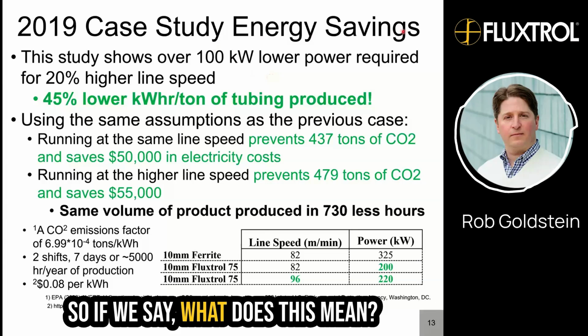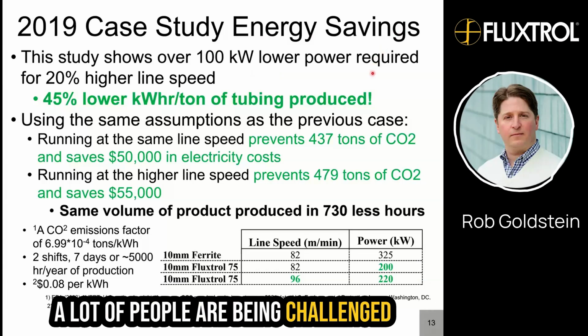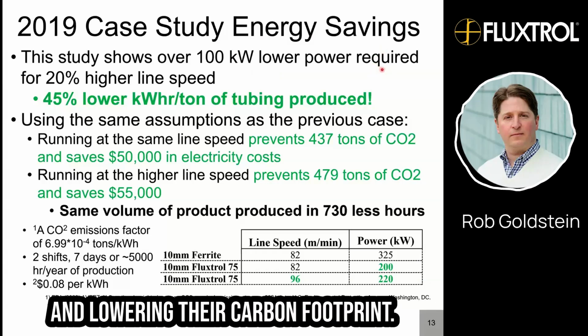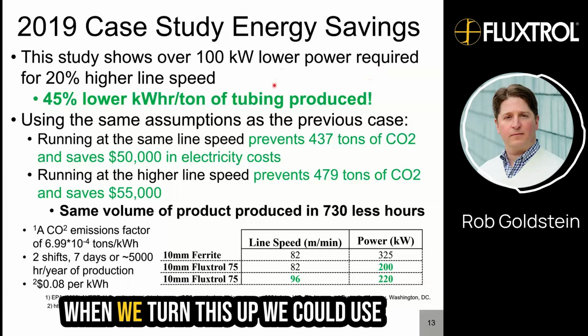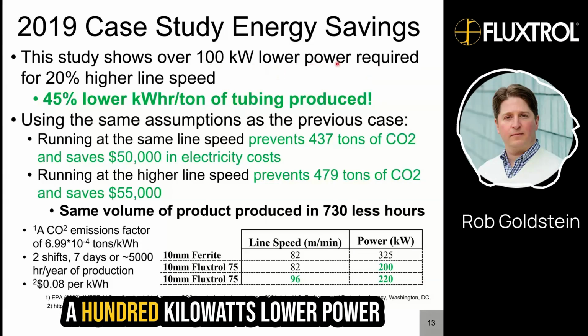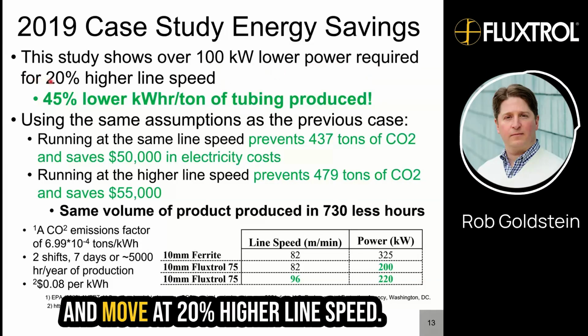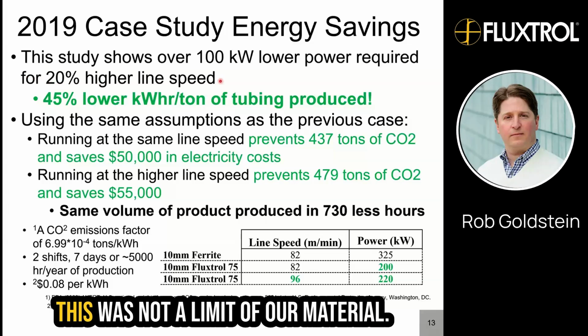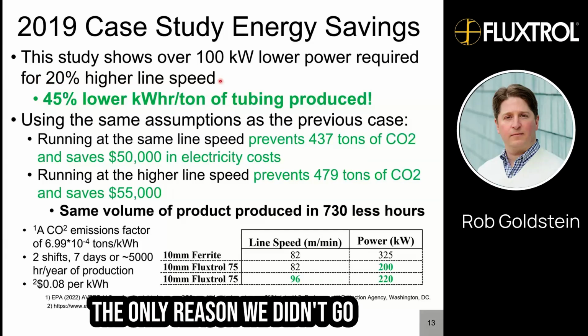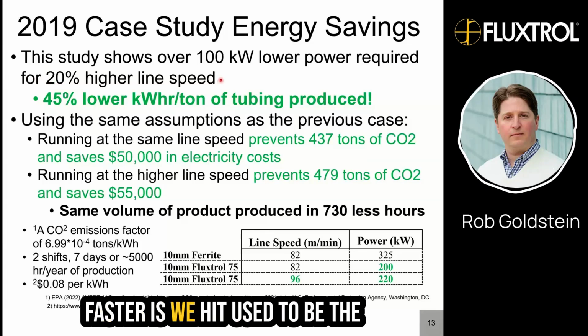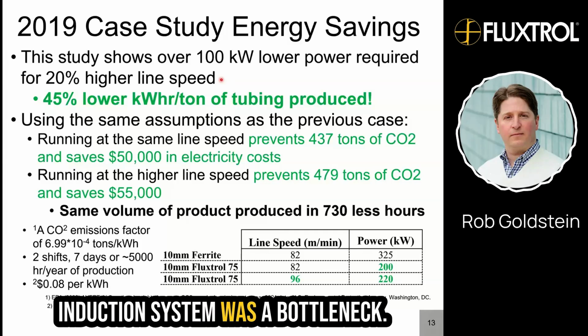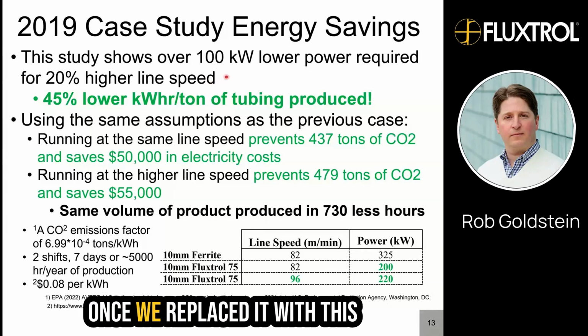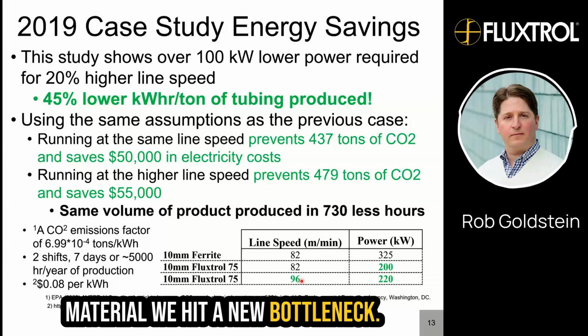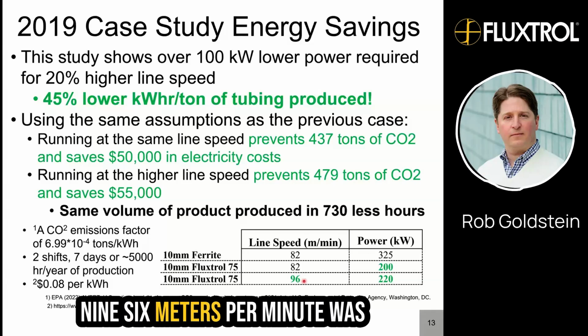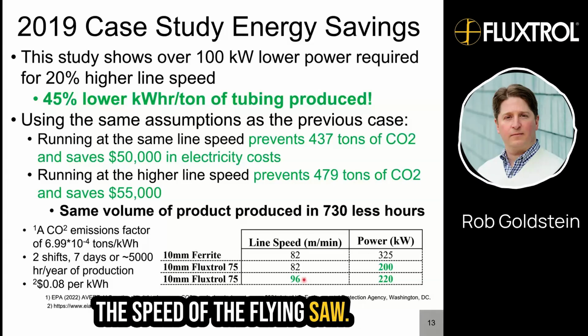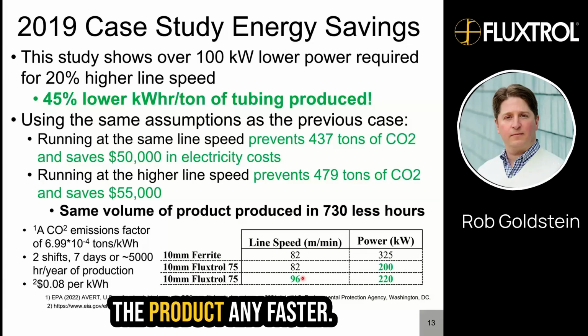So what does this mean? A lot of people are being challenged with reducing their carbon usage and lowering their carbon footprint. When we turn this up, we could use 100 kilowatts lower power and move at 20% higher line speed. This was not a limit of our material. The only reason we didn't go faster is that the induction system used to be the bottleneck. Once we replaced it with this material, we hit a new bottleneck. The next bottleneck we hit at 96 meters per minute was the speed of the flying saw, so they couldn't cut the product any faster.